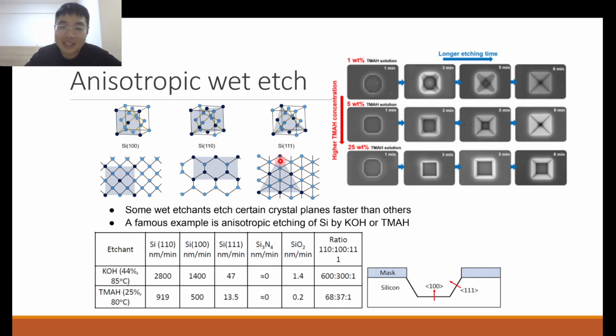Why? Because you can see that in a 111 plane, I have so many silicon atoms. That means to remove one layer of the plane, I have to break many more silicon-silicon chemical bonds. Per surface area, I have more silicon atoms. So per plane I remove in that direction, I have to break more silicon-silicon covalent bonds, and that will take longer, because it's a chemical reaction after all. It will take longer to happen.